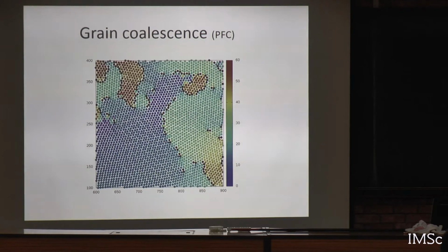But in the process, both the grains have to rotate slightly and come into alignment. You don't see such things happening at large angle grain boundaries; they are somewhat stuck. So all these extra things are happening, grain coalescence and grain breakup. So you expect that if you calculate the grain size distribution, it should be somewhat different.